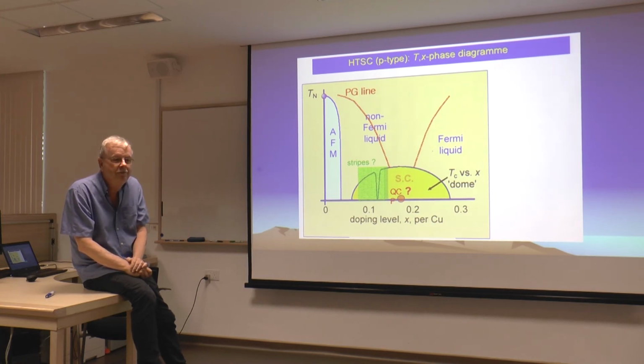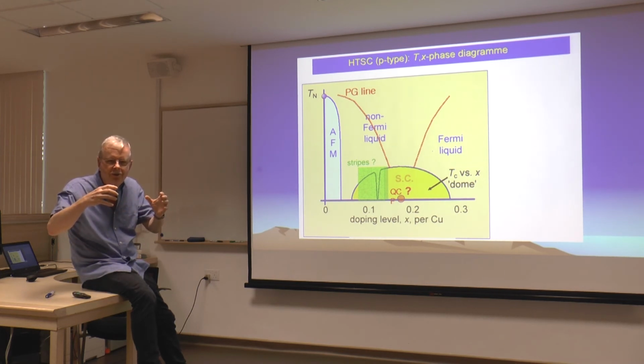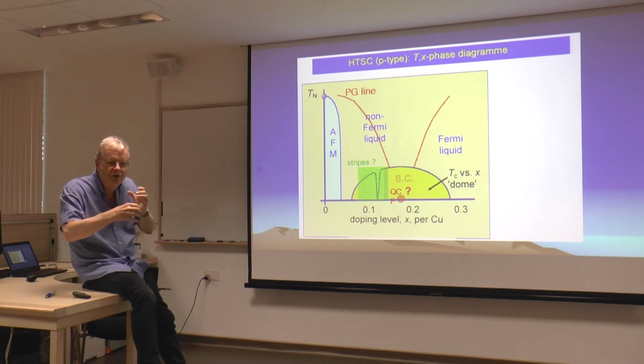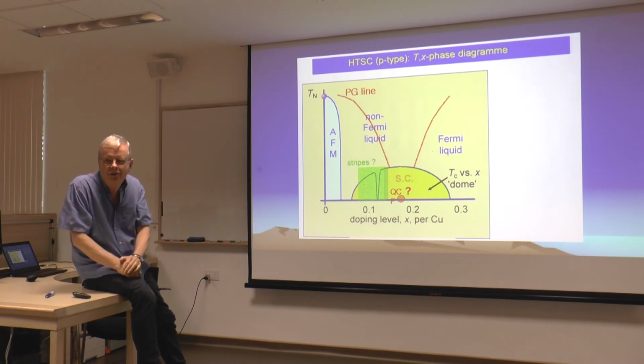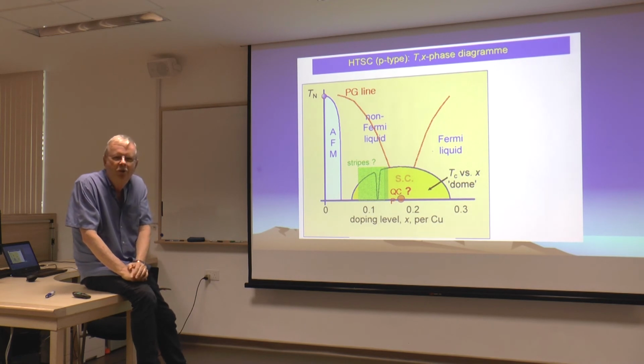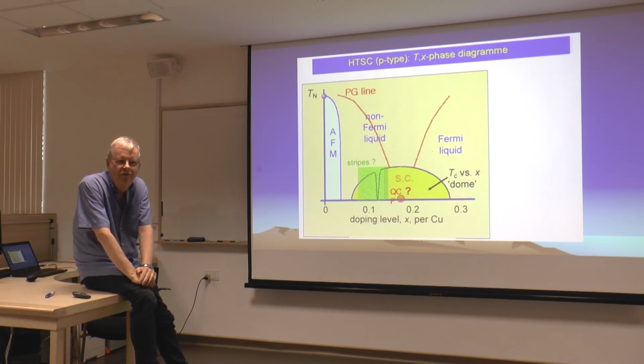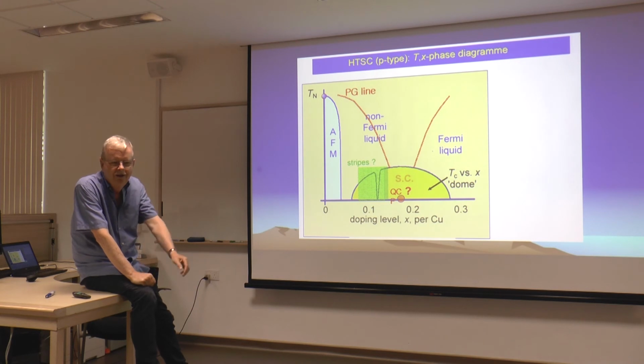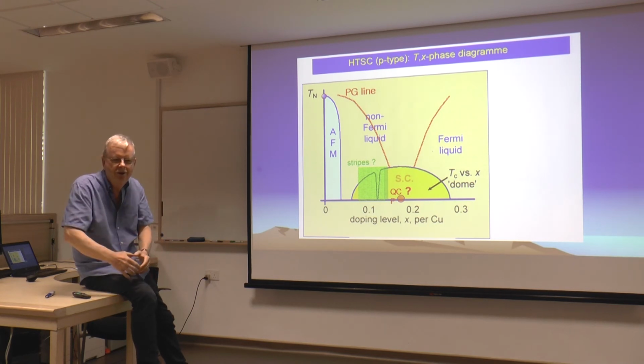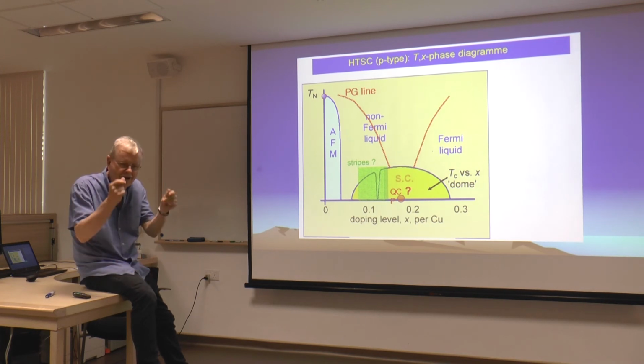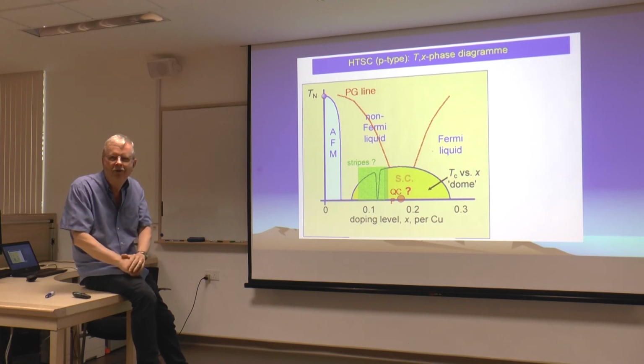One of the ways to make high magnetic fields, by the way, is to take an aluminum can and run a current in it, and then do flux compression. So in other words, you've got some flux, and then you squeeze it down to a much smaller dimension, and the flux that was in the bigger aluminum can then gets squeezed down, so the flux density is very high. And the way to do that, of course, is with plastic explosives. And so one of the ways the early YBCO people did high field studies was to go in the canyon in Los Alamos, put the sample in the middle of an aluminum sheath, put as big a current as they could get in it, and then light the explosives, and then get a very high magnetic field for a short time.